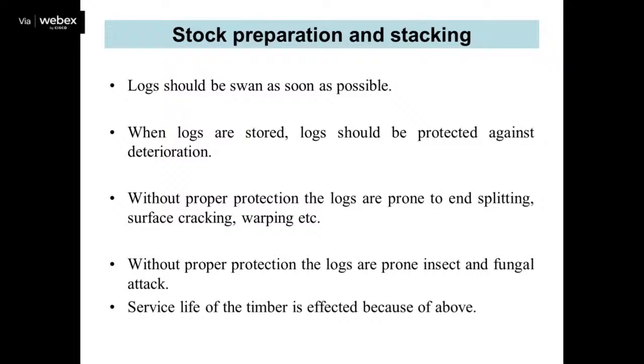There are some prerequisites before we dry or season our timber. So what are these prerequisites? When we harvest the log from the forest, as early as possible the log should be end protected. The end protection is mostly done by providing bituminous paints, and then the log should be stored properly. The log should be protected against deterioration, because logs are prone to end splitting.